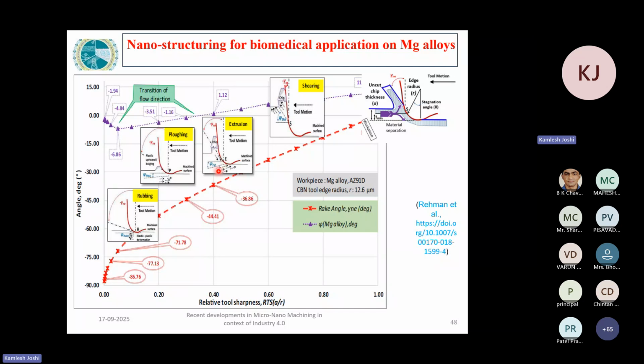The shear angle or the rake angle changes. Here you can see the rake angle is positive. It changes at around 0.4 to negative, and the process changes from shear to extrusion, which deteriorates the surface quality. Further, if we reduce the relative tool sharpness by reducing the uncut chip thickness, we cannot change the edge radius, but we can change the uncut chip thickness.